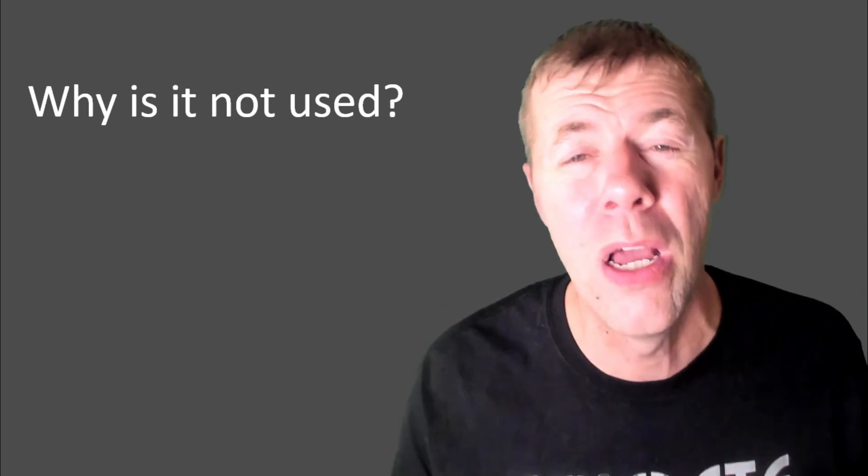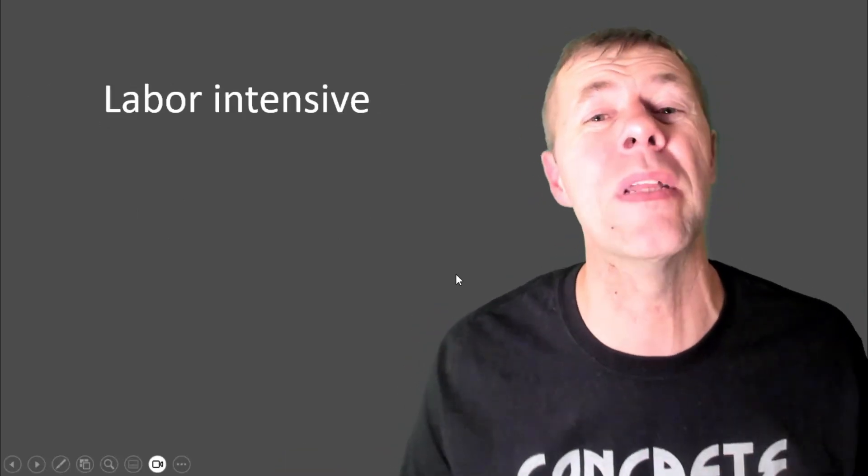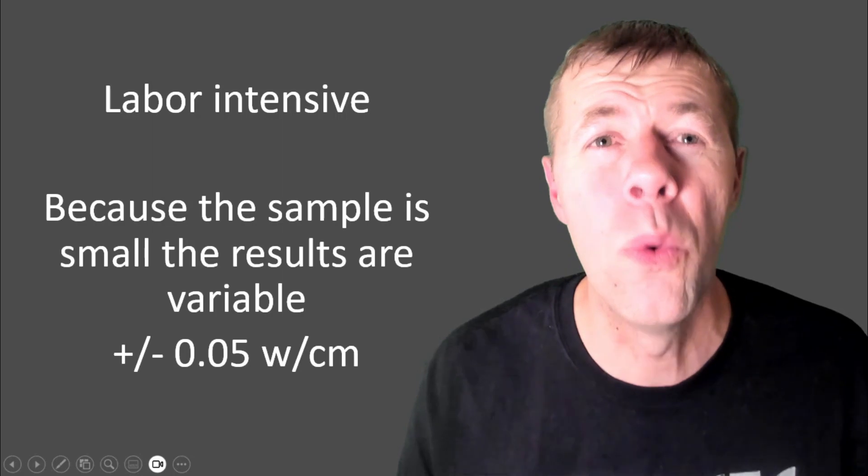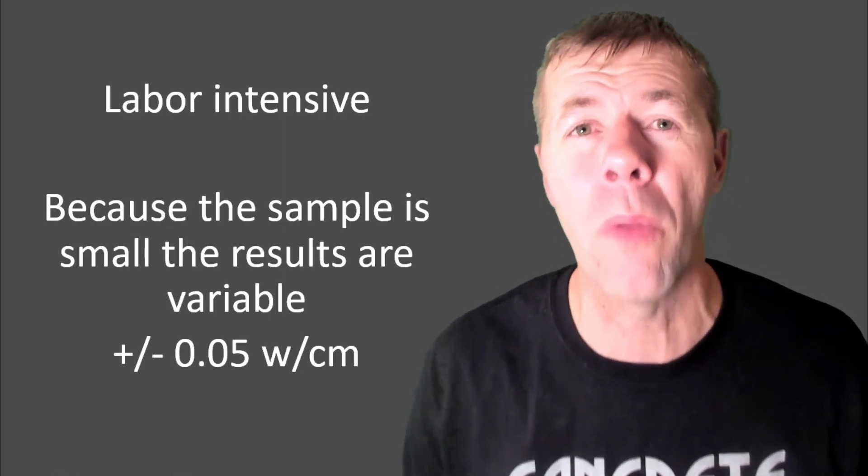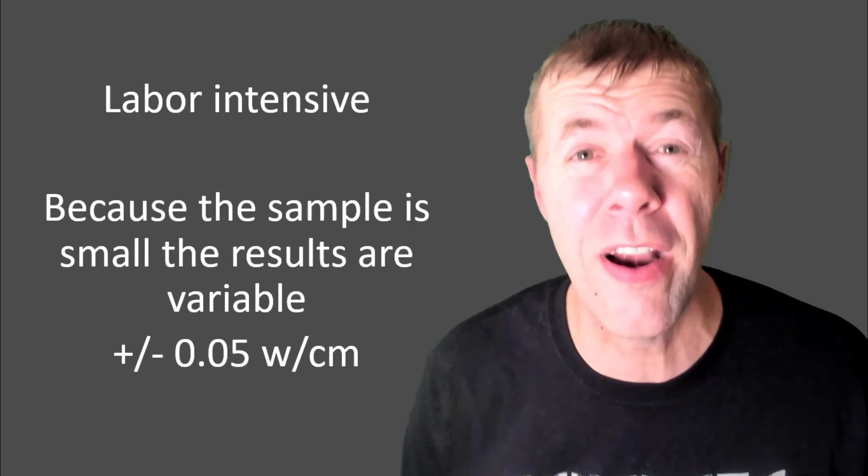So you find the water content after all that, you compare that to the cementitious content in the mixture, and you determine the water to cement ratio. So why in the world is this not used? Well, number one, it's extremely labor-intensive. Number two, because the sample is so small, the results are pretty variable, actually about plus or minus 0.05 water to cement ratio, and here's some data.